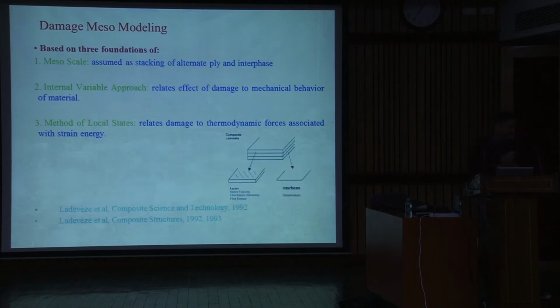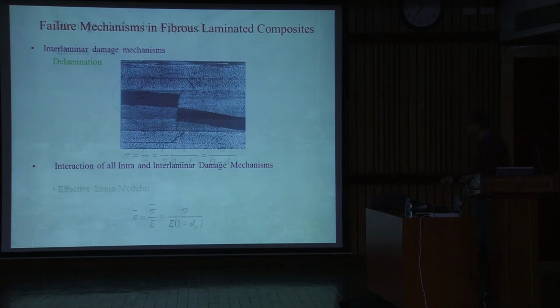Here the model that we have taken is the damage meso model. As we said, the actual structure will be like this: you have different layers joined together, with perfect bonding between two adjacent layers. Going back, you can clearly see in this picture that the laminate is an alternate stacking of plies, and you clearly see an interface between this ply and this ply. Similarly, you can see an interface between this ply and this ply, and likewise here also.